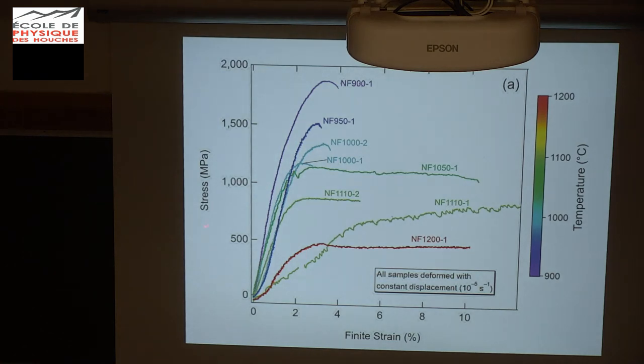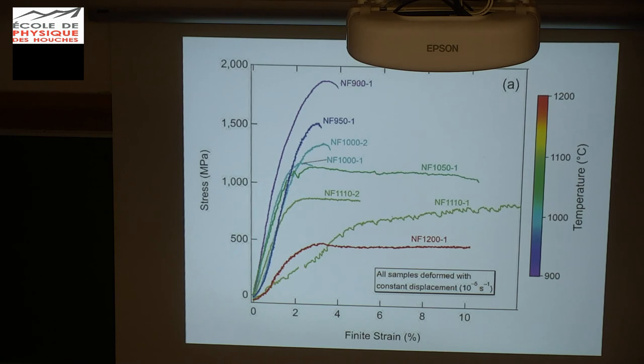Here's the deformation curve — stress in megapascals as a function of finite strain — going up to 10%. We deform at 900 degrees Celsius, where the sample is too hard and breaks. Then we increase the temperature to reach steady state. We succeed at reaching steady state, and here at the hottest temperature of 1200 degrees Celsius we get a nice steady state curve. We get steady state even though the maximum steady state stress is well above the confining pressure of 300 MPa.